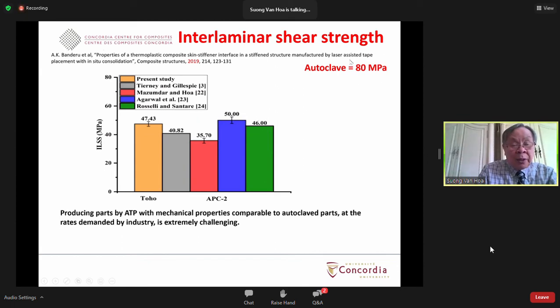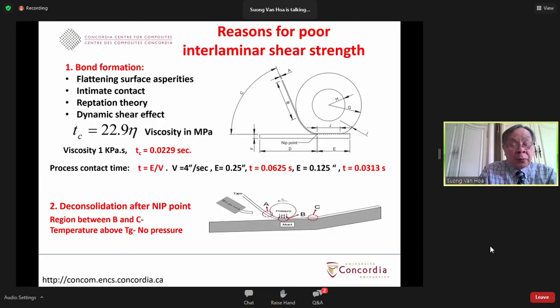Now there are many reasons why the interlaminar shear strength of the thermoplastic composite made by AFP is not as high compared to autoclave. What I find is that there are basically 2 reasons. One is the bond formation, and the second is the deconsolidation after the nip point. Bond formation, in the sense that when you take a look into the process of the AFP, you have the incoming tape here, and you have the substrate, the one that is deposited beforehand. And these two have to come together and bond together.